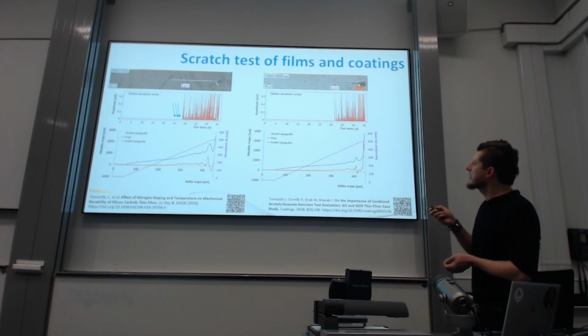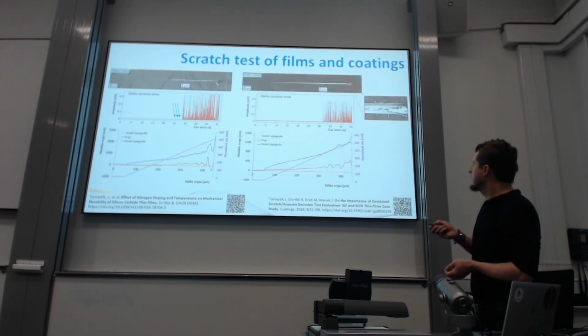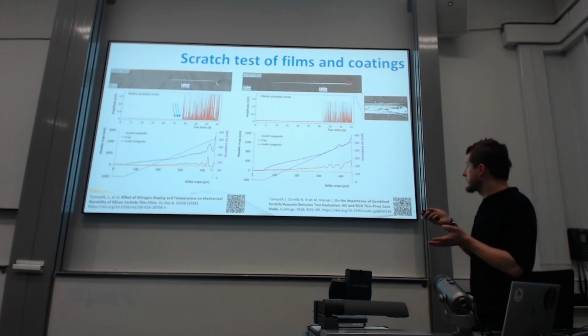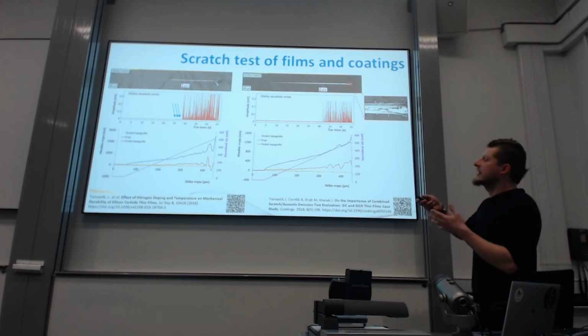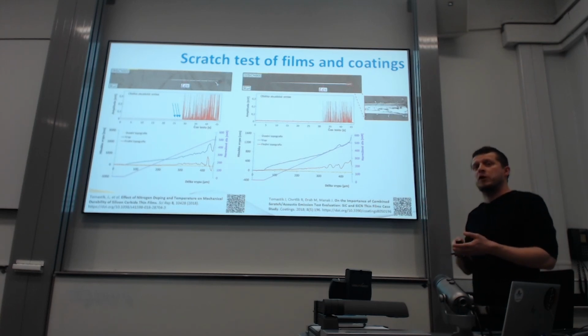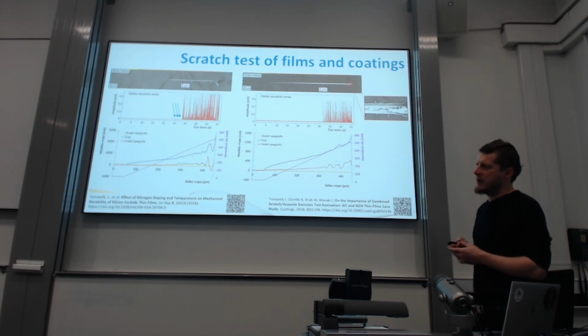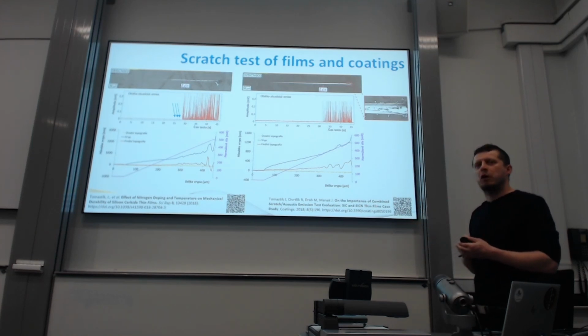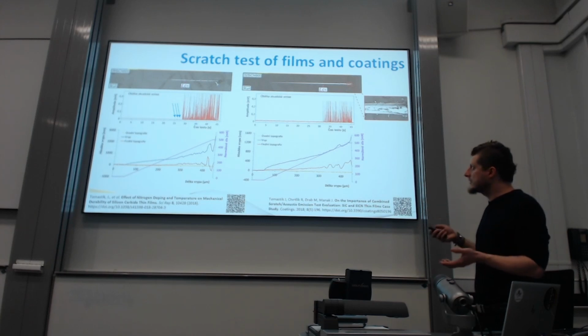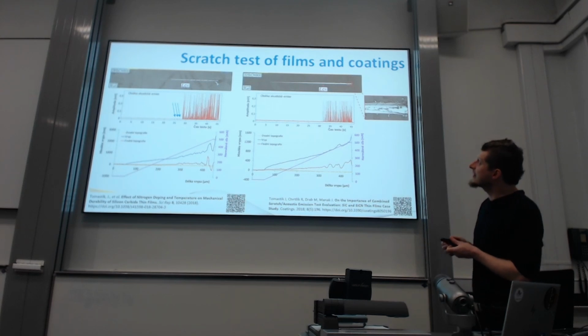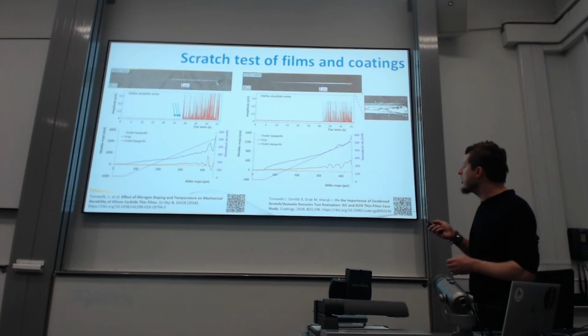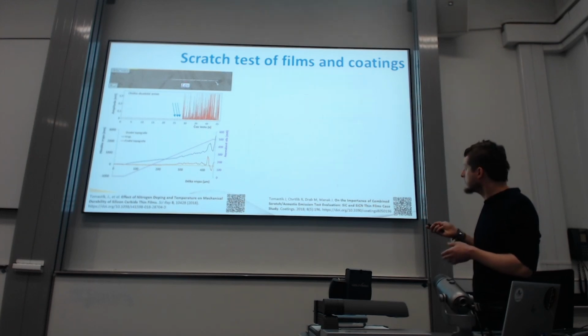Another one, silicon carbonitride, annealed at 900 in vacuum, because Tomáštík talked about several annealing approaches and analyzing silicon carbide, which will definitely be used as a future electronic material, and is already used in the Czech Republic. We have the company onsemi Semiconductors creating silicon carbide chips because they need to survive in cars. It's not about bits, it's about watts. It's so much energy, and they heat up a lot. They can handle it because silicon carbide is heat resistant. But apparently, from what I did during my dissertation, silicon carbide gets too brittle, but silicon carbonitride not so much. Through our results, silicon carbonitride prevailed in the scratch test, mostly because of an oxidation layer, let's say a triple layer, created on the surface. But that was just some results.